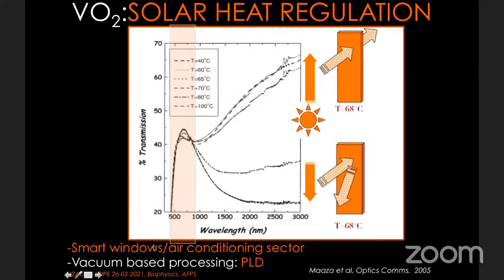That change of the refractive index induces something which is extremely important. If you have a glass slide coated with VO2, at low temperature you will find the transmission in the infrared and near infrared is quite high. The transmission of this glass coated with VO2 is above 50%, as you can see. This is the optical transmission, measured. When the film is hot, the optical transmission of this glass coated with VO2 decreases, as you can see, close to 20%, it can reach zero.